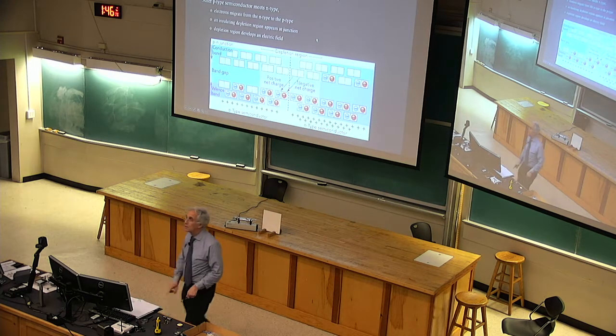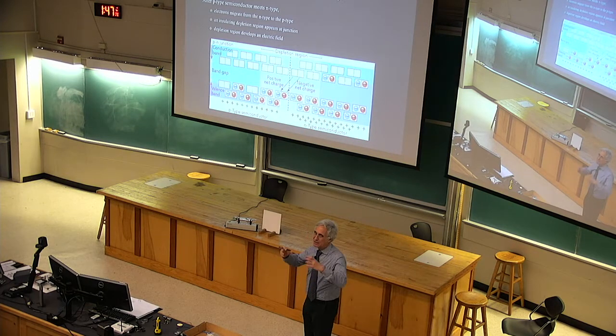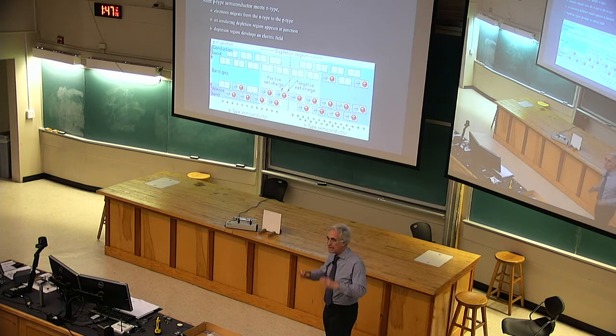poof, they touched. And this is not how diodes are made. They don't actually make two materials and touch them. They build them together. But you could do this in principle. You make the two materials and touch them. When you touch them, the charges do migrate. The electrons in the conduction levels near the junction, this is called the PN junction, P and N, because you're bringing together P and N semiconductors, do migrate across it.